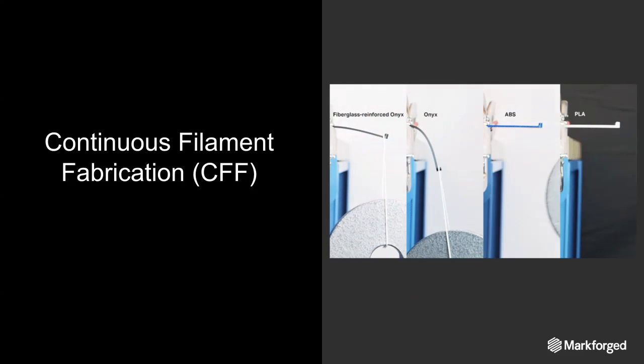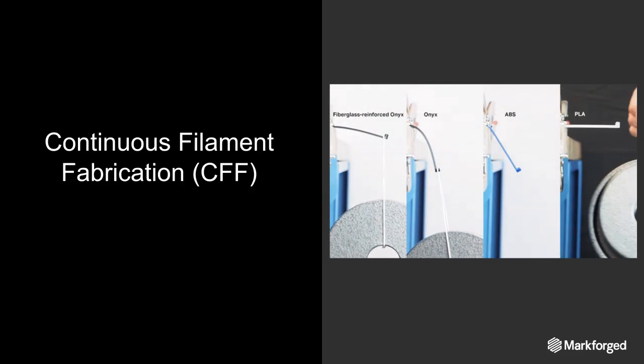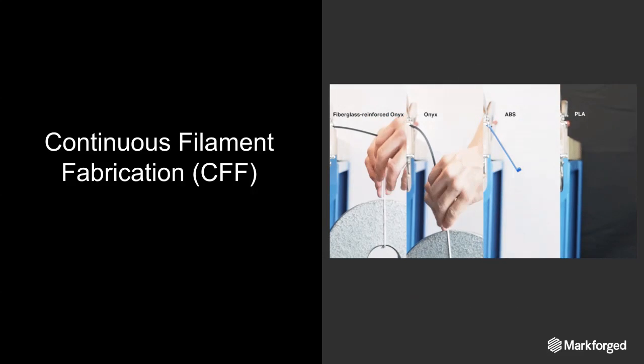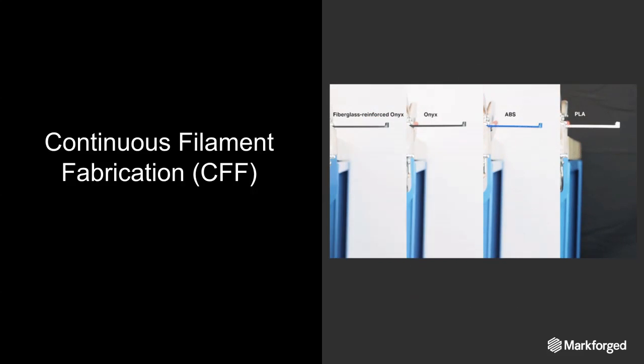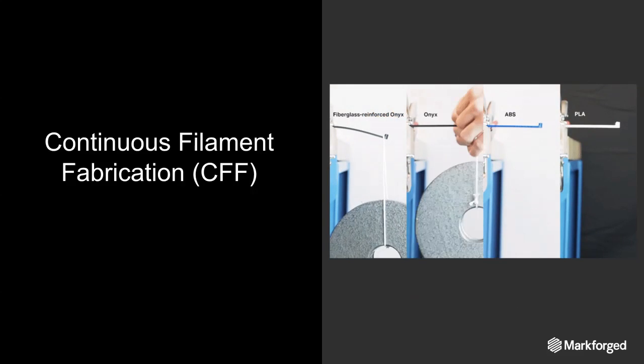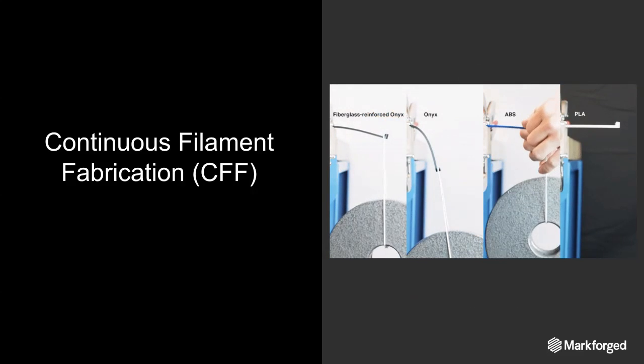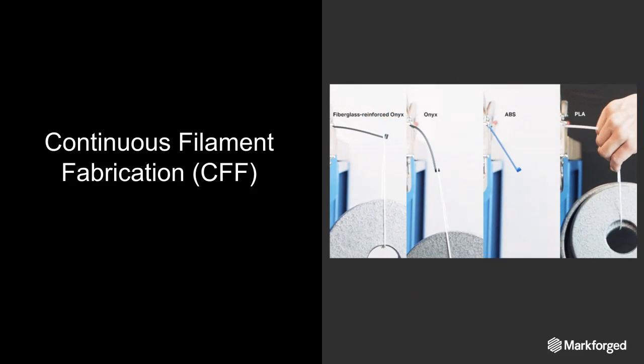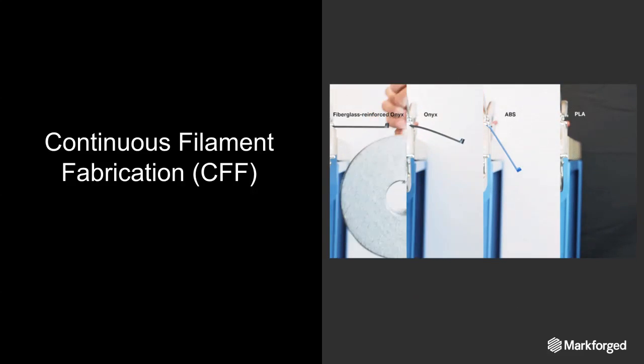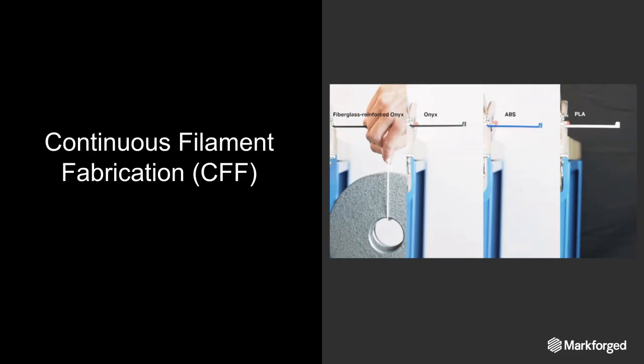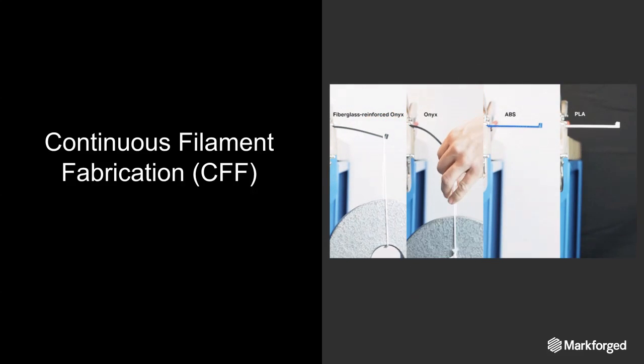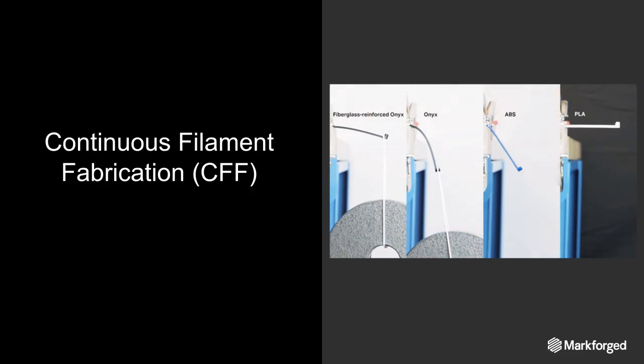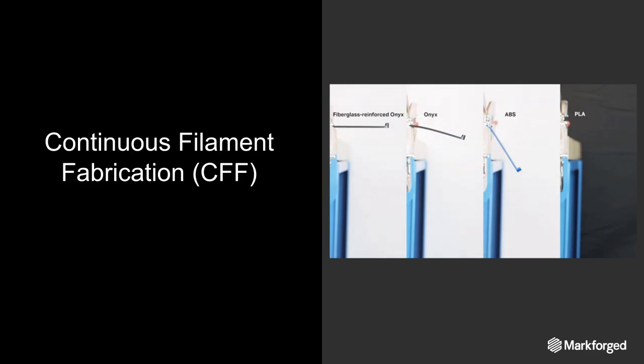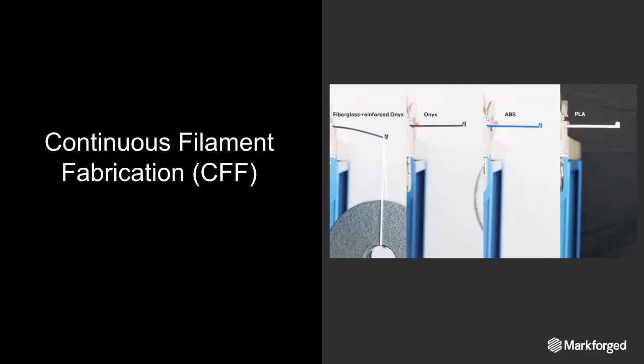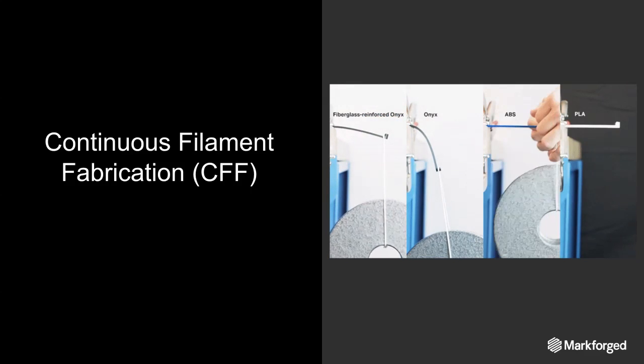Here's a video of that strength in action. On the left of the video is a fiberglass reinforced Onyx beam, printed on a Markforged printer. Second from the left is Onyx, so just the thermoplastic without any reinforcement. And the other two are typical 3D printing thermoplastics, ABS and PLA. 7.5 pounds was hung from each of the beams. And while both the ABS and PLA beams snap, the composite beam deflects a little bit and then goes back to its original shape after the weight is removed.